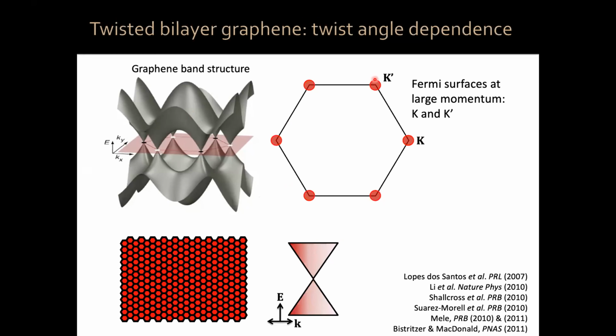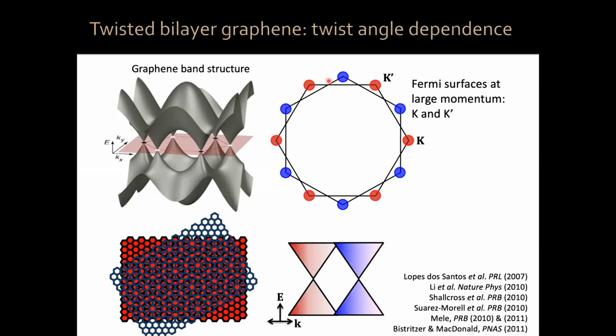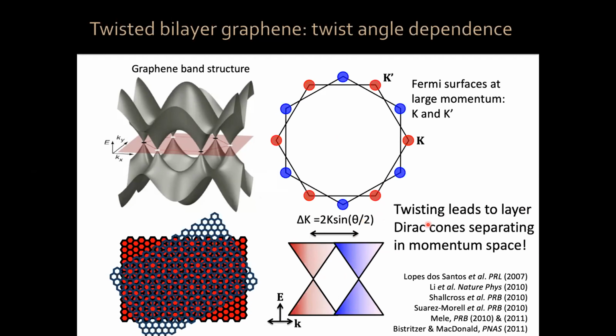K and K prime. So now, if you put another graphene sheet on top and it's perfectly aligned to it, then the reciprocal spaces are perfectly aligned. The Dirac cones are on top of each other, okay? Now, what happens if you now rotate in real space? Well, in reciprocal space, the Brillouin zone also gets rotated, okay? So rotation in real space leads to separation in momentum space, and the separation between these Dirac cones is proportional to the sine of half the rotation angle, okay? So twisting leads to layered Dirac cones separating in momentum space.